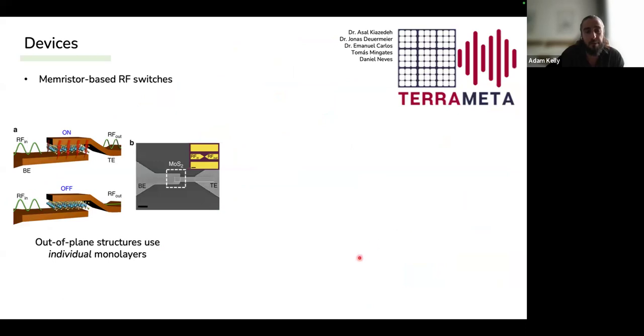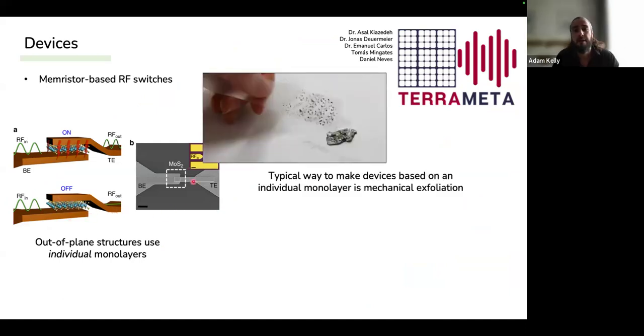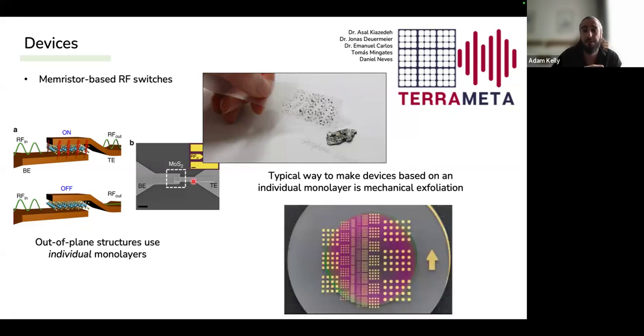Another device that we tend to make is these memristors. When you have a memristor, the way it's often done is with an out-of-plane structure. So we take a bottom electrode, we take an individual monolayer of MoS2, for example, and we put it on top of the electrode, and then we deposit a top electrode on top. Now, typically the way people take individual monolayers and place them is by mechanical exfoliation, but you can imagine if you have to make a wafer scale amount of devices, you're not going to be going around mechanically exfoliating each individual nanosheet and placing it, because this is extremely tedious and it's a great way to lose PhD students.